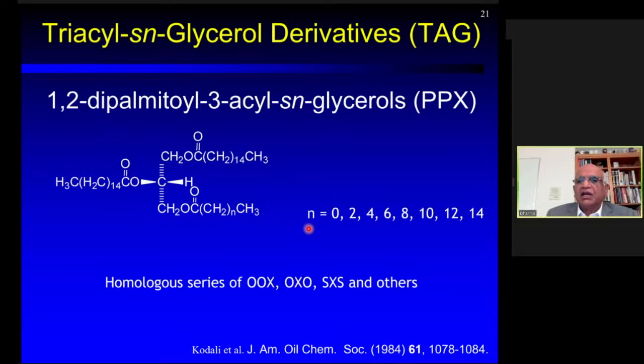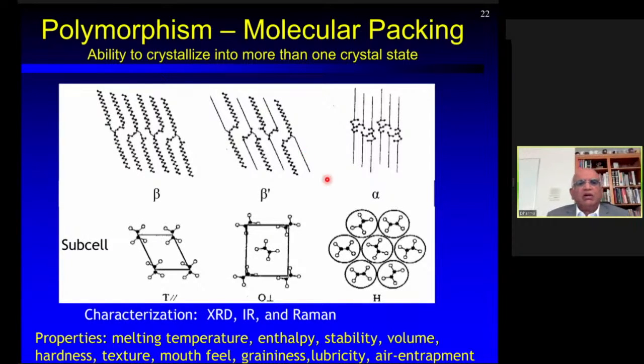Especially these long acyl chain containing molecules have the unique ability to crystallize into more than one crystal state. This phenomenon is called polymorphism. The classification of polymorphism is shown here: beta, beta prime, and alpha. This is based on the subcell structure, which is shown here. The differentiation or characterization of these polymorphs can be done with powder X-ray diffraction, infrared or Raman spectroscopy. The subcell structure, on the short axis, how these zigzag chains are packed in relation to each other, is the one that defines the polymorph.